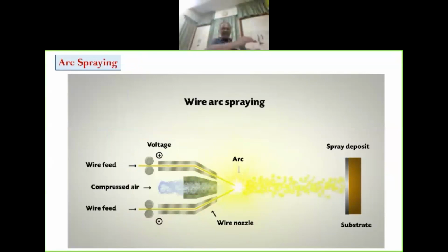Its younger cousin is this. Simple to understand. Arc spray, developed long back. I have a positive wire, I have a negative wire. Bring them close together, get an arc. The tip will melt away, and a compressed air jet will do the rest. Meanwhile, keep on using rollers, keep on advancing the wire. Very good for electrically conductive wires. For everything electrically conductive that is available as a wire, you can develop a coating very quickly.